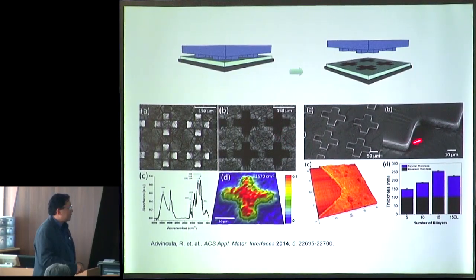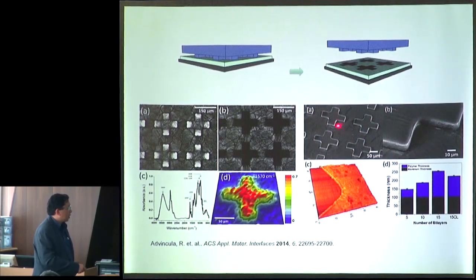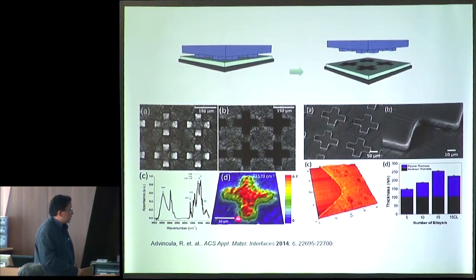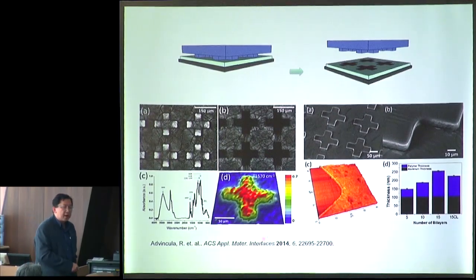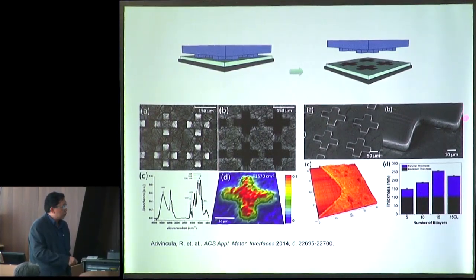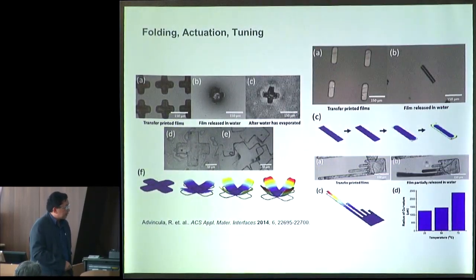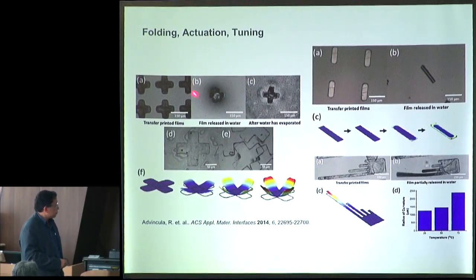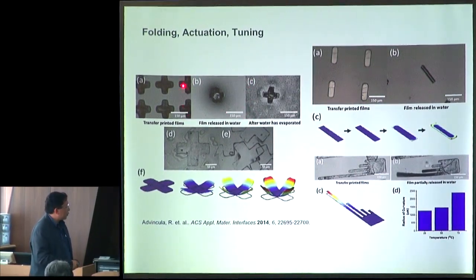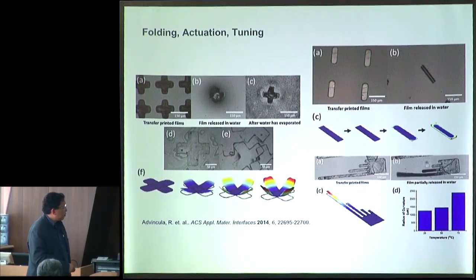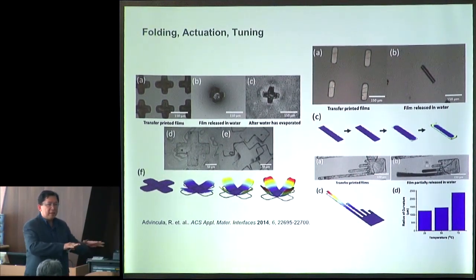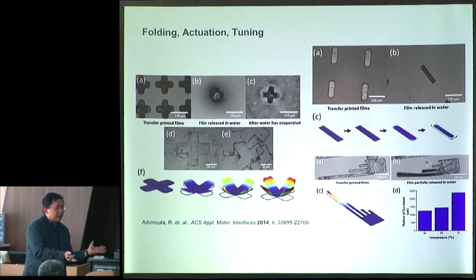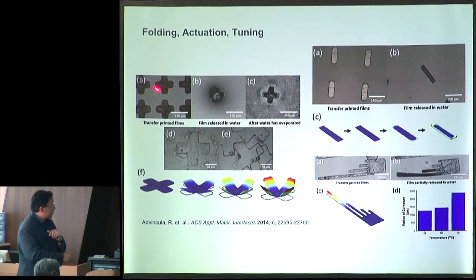We can make very nice edge patterns, edges that are high fidelity. In this case, a cross. Again, the composition was monitored by IR. The structure was observed by SEM and AFM. And these are the different objects we printed, or rather lithographically patterned. So we have crosses here, and you put them in water, they start moving. And then the independent ones, they start folding. So we observe this folding mechanism in this process.